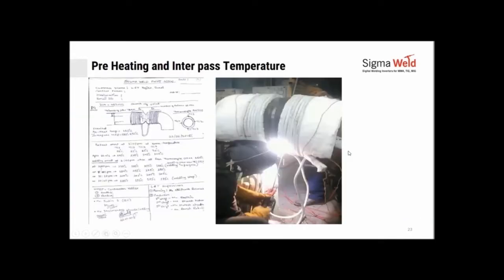This is another trial done for its equipment in use for pipe to elbow welding. During welding for this material of P91, the preheated temperature was about 150 degrees. It was achieved after 15 minutes. You can see that. And the job thickness is 72 millimeters. Achieved in 15 minutes, 150 degrees.